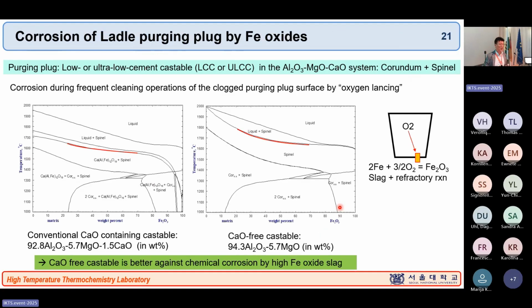And this is another example I did. I made it with my colleague at Almatis. They are producing the porous plug with a high alumina. So here they have a conventional plug containing a little bit of CaO and then alumina and MgO, like this composition. And then they install this and make a porous plug. And this porous plug works as an oxygen lance, with oxygen going into the porous plug and making oxidation, bubbling inside this one.